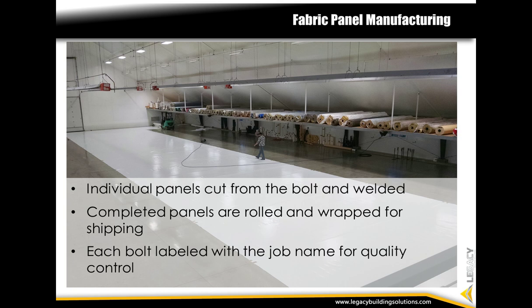First, each fabric panel is carefully cut from the roll. The cutting floor is marked at regular intervals to verify the accuracy of the cuts. Then the cut panels are permanently welded using a hot air or wedge weld to form a wall or roof panel, typically 20 feet wide. Seams can be produced at a rate of 20 feet per minute. So the fabric panel manufacturing is a very efficient process.